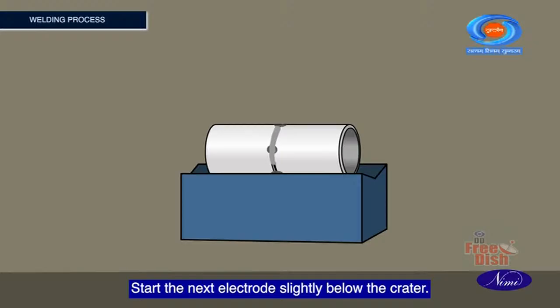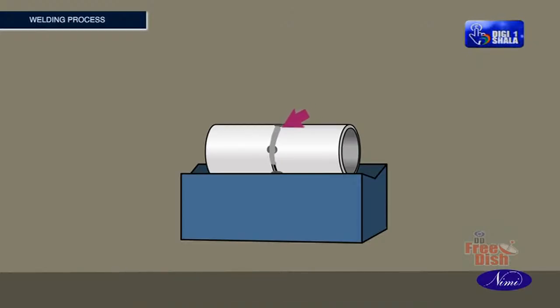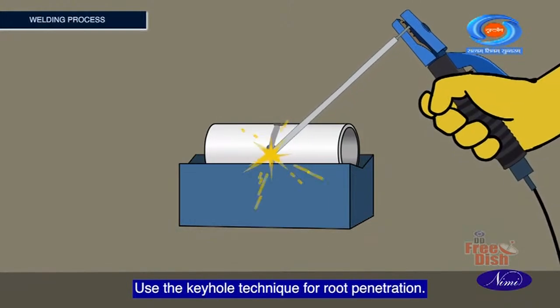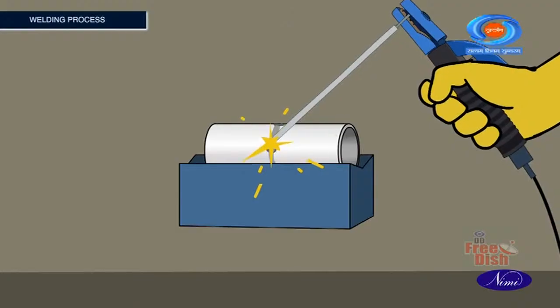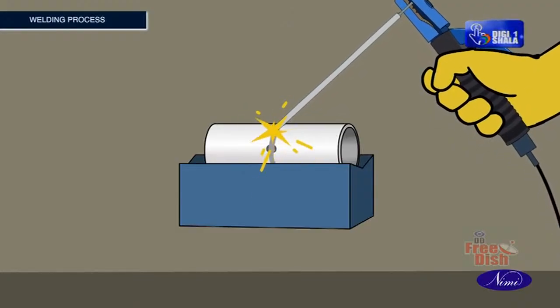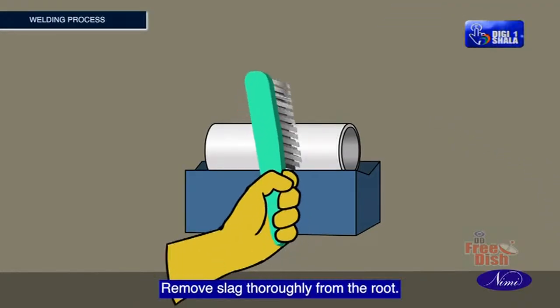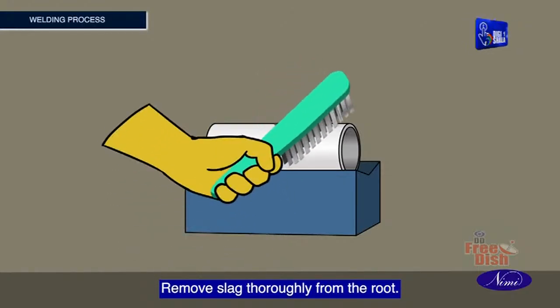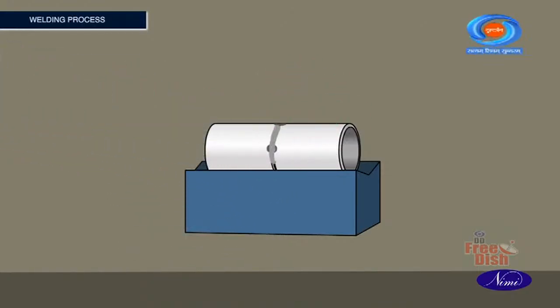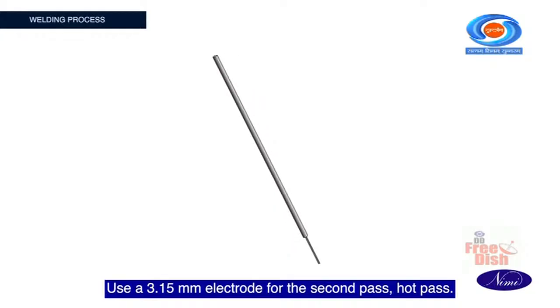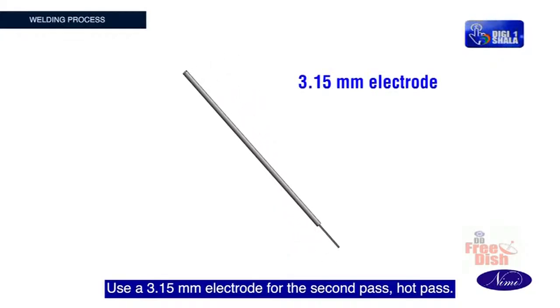Start the next electrode slightly below the crater. Use the keyhole technique for root penetration. Remove slag thoroughly from the root. Use a 3.15 mm electrode for the second pass, hot pass.